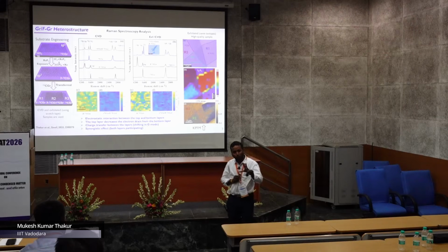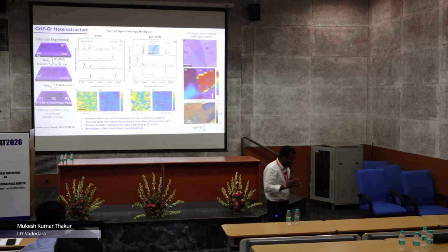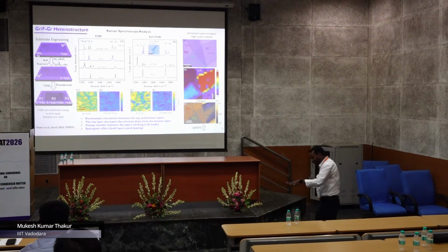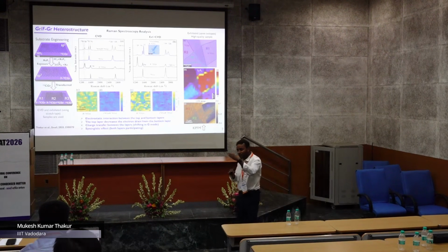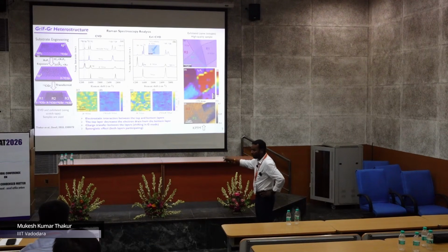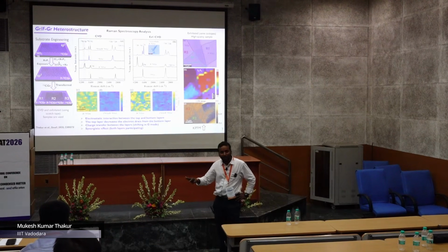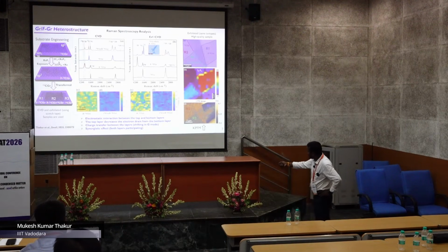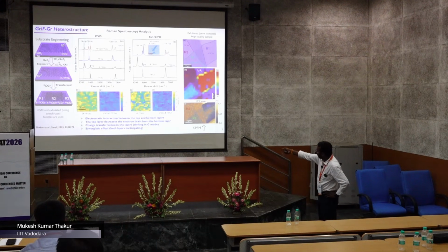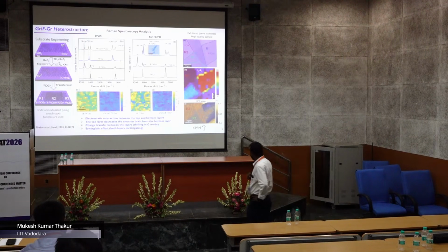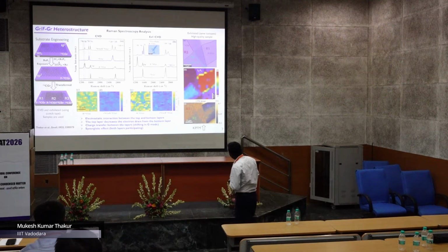Basically, the top and bottom layers are both interacting. Okay, and we say the interaction is electrostatic. Also, when we don't have this, fluorine is not stable. So when you don't have any top layer, fluorine will migrate, right? So somehow it also prevents the electron drain from the bottom layer. And this is a kind of synergetic effect. And also we observe a shift in the G mode, which is also an indicator of charge transfer. So this is happening here. Okay, very nice. So passivation and this thing.